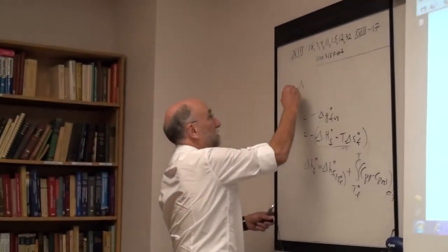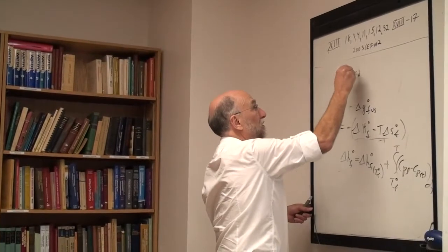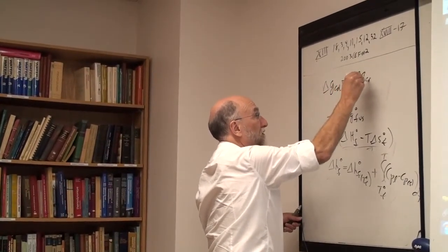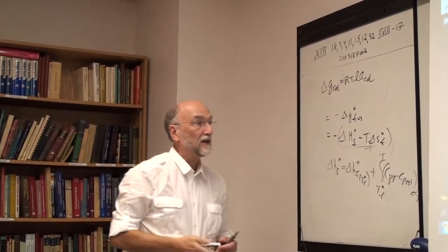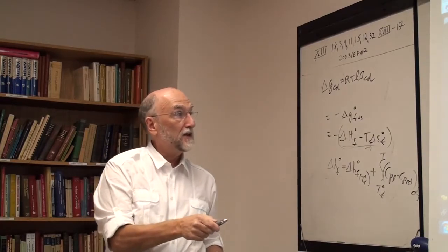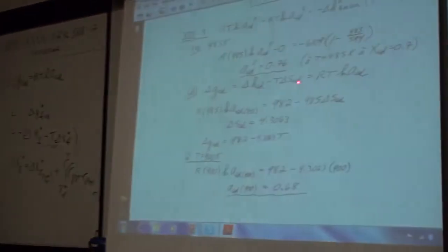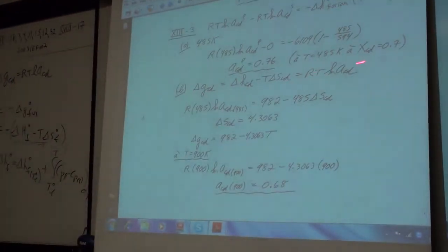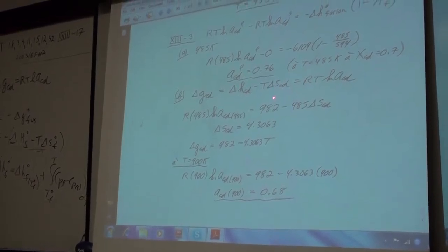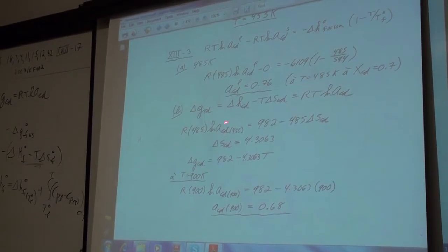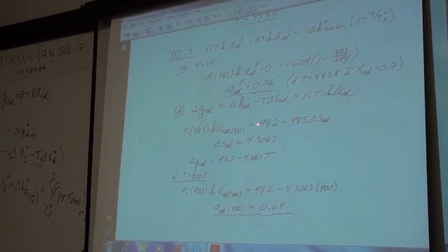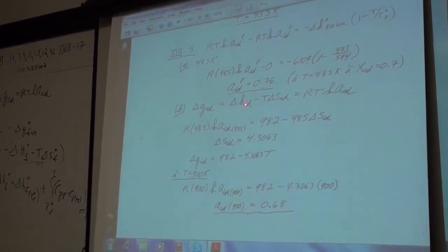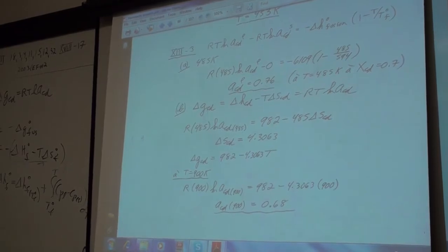Okay, so what I'll have is the partial Gibbs energy of cadmium is RT log activity of cadmium, and I can calculate that value, so that's equal to the partial heat of mixing minus T delta S of mixing. The RT log activity is the partial heat minus T times the partial entropy. Okay, so the partial heat has been measured in a separate experiment. The partial heat of mixing of cadmium is 982.